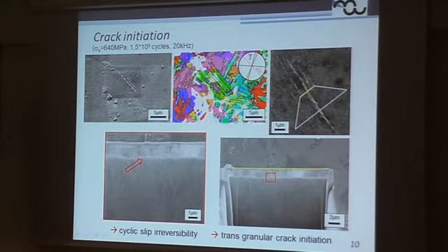And we would say that we have fatigue crack initiation in the very high cycle fatigue regime, but that the surrounding microstructure acts as an effective barrier against fatigue crack propagation.